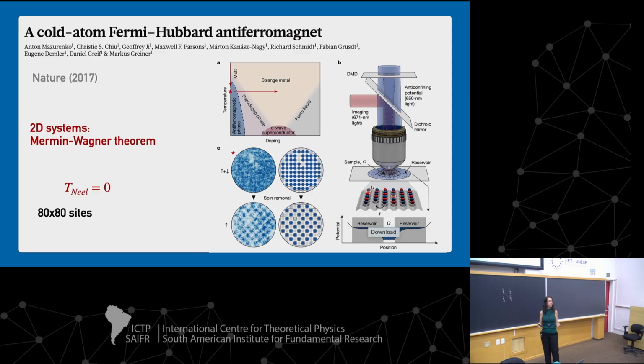It's very broadly based, and it says you cannot have order in 2D. And it has very wide implications. This, for instance, is why a single layer of graphene ripples. It's not a single flat layer, because it's not stable. It has to have ripples, because it would take a 2D system to be completely flat, to organize perfectly in 2D. So it has many implications.